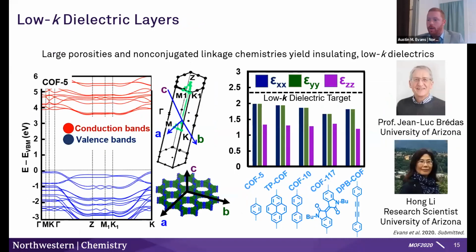And having been able to accomplish that goal, we were really interested in building electronic devices out of these materials. That's been an interest for a very long time. But if you look at the electronic structure diagram here, what you'll find is that these are highly insulating. I mean, the band gap is enormous. And largely that arises from the fact that the boronate ester linkage is not conjugated at all. And so your in-plane electronic conductivities are going to be low in that case.